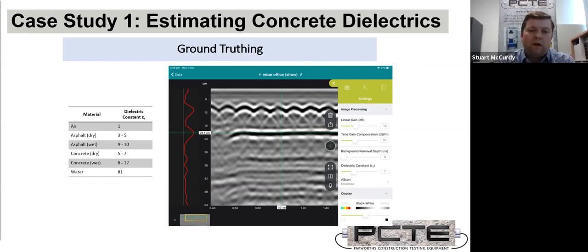Now we're going to get into ground truthing. So I've moved down to the bottom of the slab, and it's telling me that the slab's 211 mil thick in this scan. But I actually know it's 180 mil because there was an area of the slab that I could physically measure as 180. So what I need to do is change that dielectric so that the bottom of that slab is correct. So when you're picking a point, you want to pick where the peak is in the A scan. That's where you've changed material.